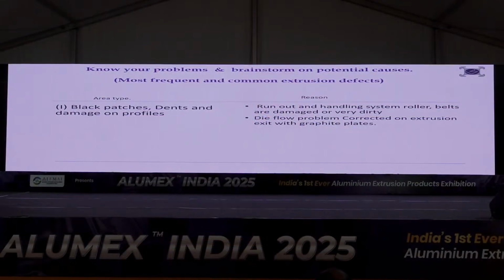Profile deformation, I have already discussed. Black patches, dents, and damage on the profiles. Most of the time, runout itself is bad. Roller belts are dirty, oily. Somebody uses graphite pieces and presses them. Better correct your die. Don't do like this. These are not the die correctors. Your die corrector is employed and he must do it. You must make sure the extrusion comes out absolutely straight from the press mouth. You cannot run it with compromise lifelong.